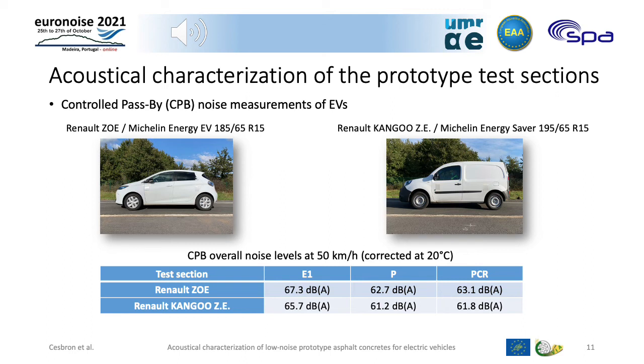In the table you can see the CPB overall noise levels at 50 kph corrected at the temperature of 20 degrees Celsius. Noise reduction at 50 kph by comparison with the reference surface E1 is 4.2 dBA for PCR and 4.6 dBA for test section P in the case of the Renault Zoe. In the case of the Renault Kangoo ZE, the noise reduction is 3.9 dBA for the PCR test section and 4.5 dBA for the test section P. It is also observed that the Renault Kangoo ZE is about 1.5 dBA quieter than the Renault Zoe.